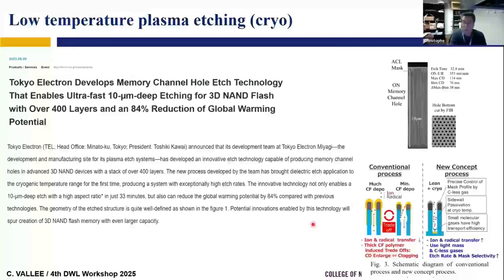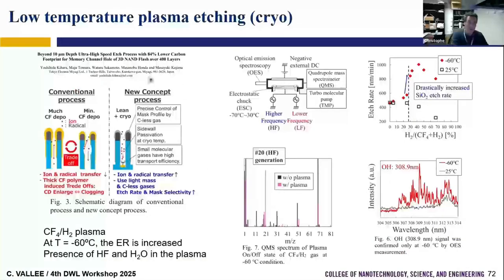So this is what was proposed, for example, in 2023 by Tokyo Electron, when they said, we develop for the high aspect ratio for 3D NAND, a new process where we use a very low temperature, so cryo etching. And using a cryo etching, we can do the high aspect ratio etching, and in addition, we can reduce by 84% the use of the gas, so it's better for global warming. Because when we use the cryo etching process, in fact, they can enhance the etch rate, so they etch faster, and they have a very good selectivity, as they don't have the issue with too much fluorocarbon deposition because they play with the physisorption. So I took this illustration from the papers they presented here in 2023.